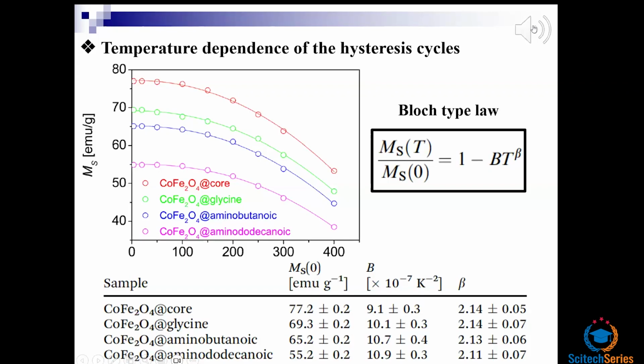So all these curves can be curve fitted with the standard Bloch-type law, in which the normalized saturation magnetization goes with the temperature, and there is an exponent beta you can extract from the fitting. So again, symbols in the plot are experimental data, and the solid lines are the best curve fitting using the Bloch-type law equation. The table in the lower part of the slide collects the saturation magnetization, the B coefficient, and the beta exponent. You can see all the beta exponents are about the same, around 2.1.